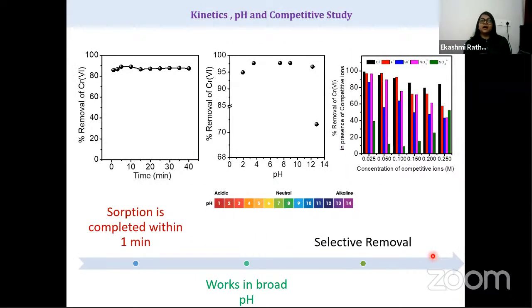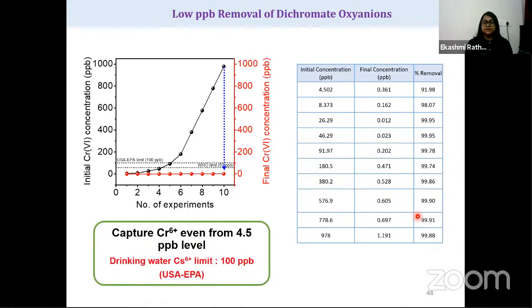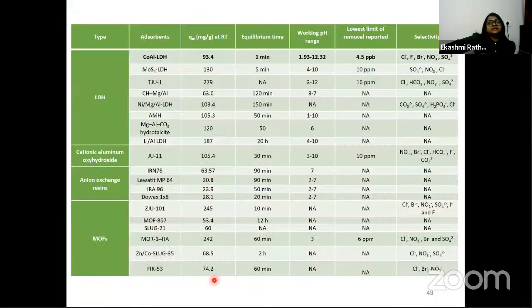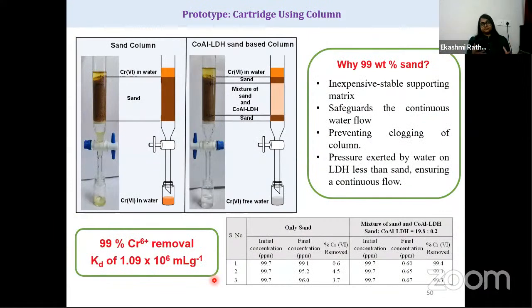I carried out similar kinetics, pH, and competitive ion studies, and we found that sorption is completed within a minute, and it can remove more than 90% of the chromium ions effectively. Even in the presence of other anions like chloride, fluoride, bromide, or nitrates, it shows that it's selective in nature. With these amazing properties, we checked low parts per billion removal. Our material could capture even from the 4.5 ppb level, while the drinking water limit given by the USA EPA is 100 parts per billion. We compared our results with other materials, and we found that our material is the best one. With this, I thought, let's make a prototype and see how it will work.